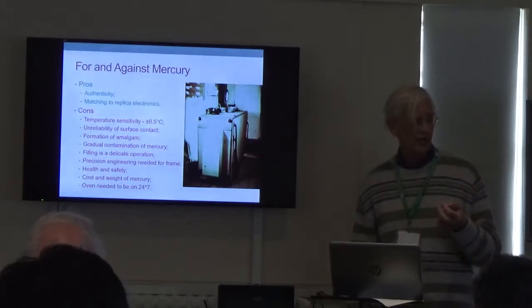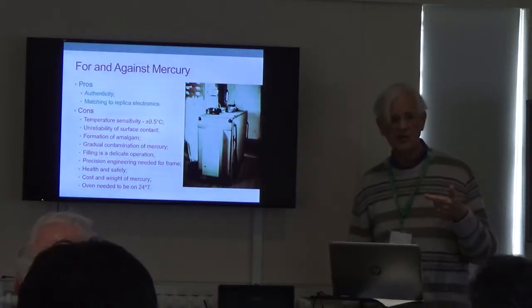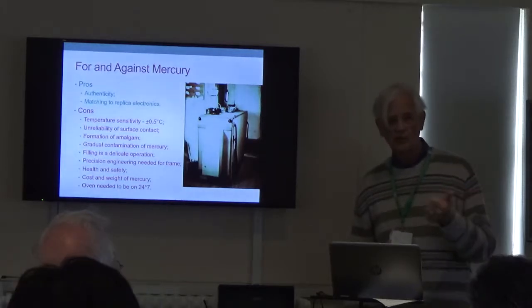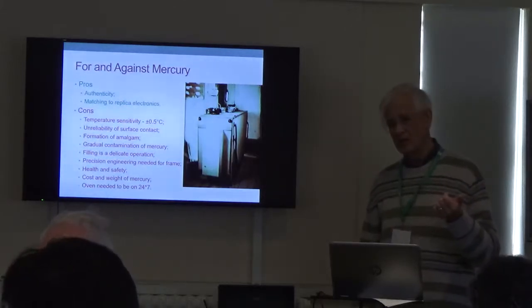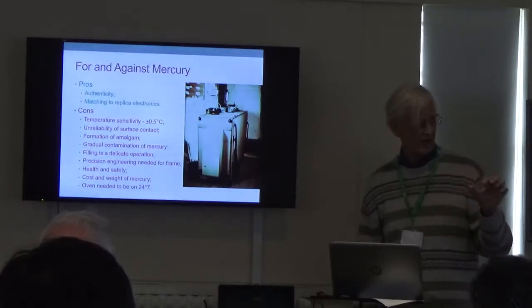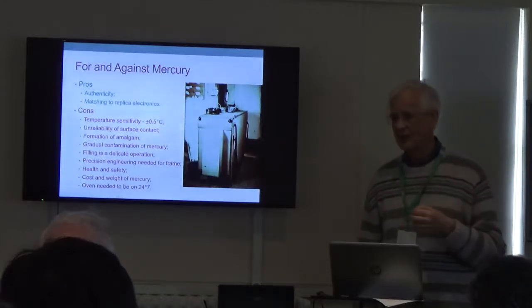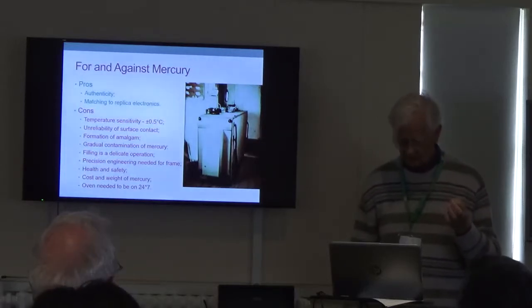The mercury degraded progressively. Amalgams: mercury dissolves any reasonably reactive metal, so it'll take the zinc out of brass. If you ever put a dab of mercury on anything aluminium, it's spectacular. Aluminium is only stable in a normal environment because of the oxide film on it. If you put a touch of mercury on, you get an amalgam on a scratch, and the surface of the amalgam does not form a passivating film, and a white whisker of growth comes up, and within a matter of hours the whole thing is lace. So it's a dodgy material to work with.